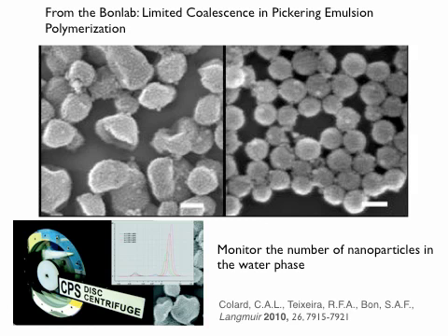Now, if you run out of particles too quickly, say at 70% conversion, and your latex is still growing, you'll end up with a hydrophobic surface where there are no particles present, the system becomes unstable, and they bump into each other. You get coagulation. That's what you see on the picture on the left. You get limited coagulation, so 2 or 3 particles bump into each other. The little ones rearrange themselves over the surface, and you get a bit of a popcorn type of structure. Now, if you added more particles to this, you'll end up with a really nice spherical armored polymer latex in this case.